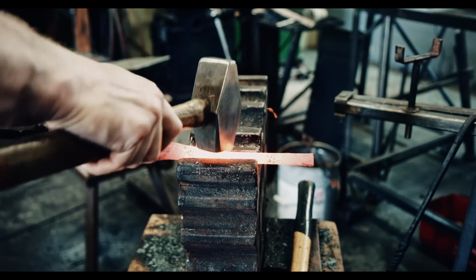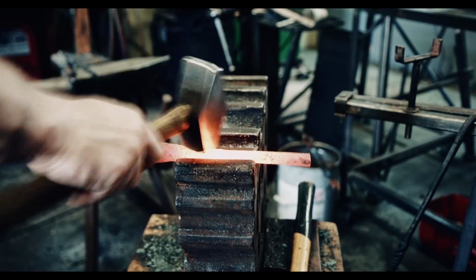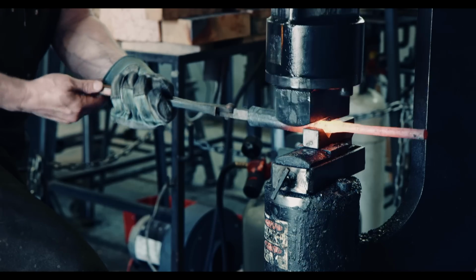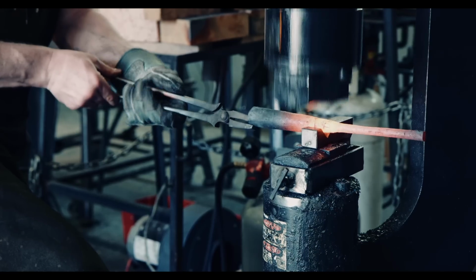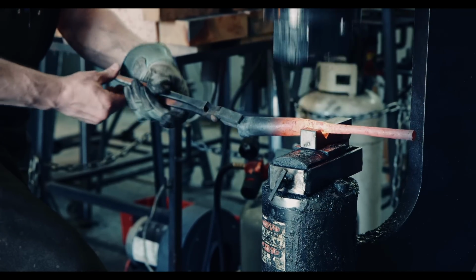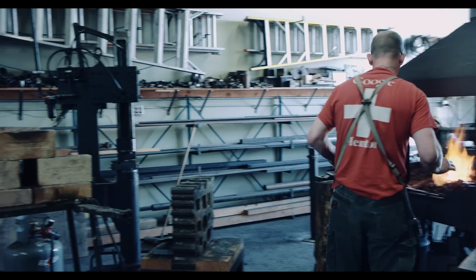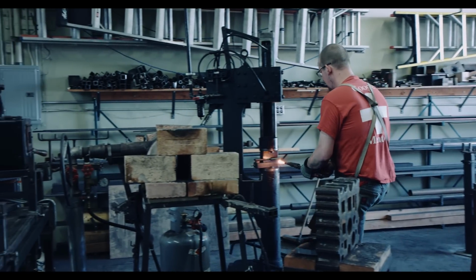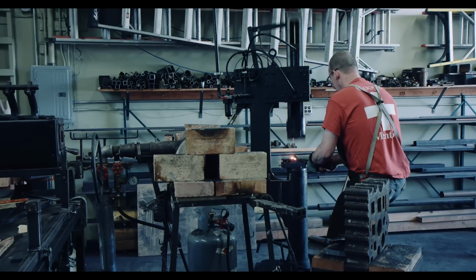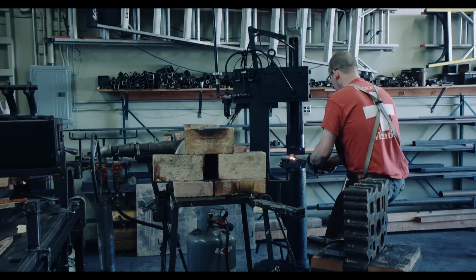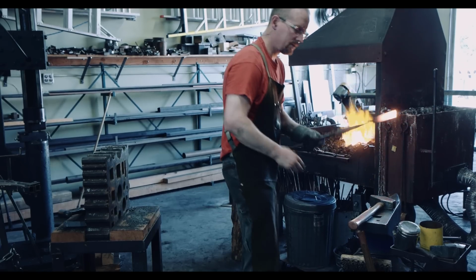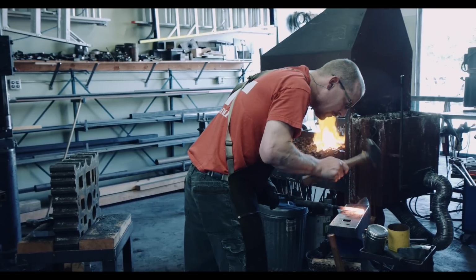After I'm happy with the taper, the part of the core that sticks out needs to be prepared. As with all my pattern welding, I like bars that are roughly 3/8 of an inch thick, that's about 9 millimeters. I am also forging in a small tip, but that's about it for preparing the core of the spear.